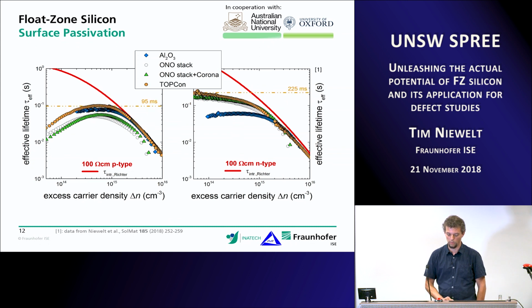However, the great thing is when we look at our TOPCon passivation, so this tunneling oxide passivation scheme that Fraunhofer ISE has developed, and there we see that we reach 95 milliseconds on 100 ohm centimeter P-type wafers and 225 milliseconds on N-type wafers, which is, to our knowledge, the highest lifetime ever reported for float zone silicon, or for silicon overall.